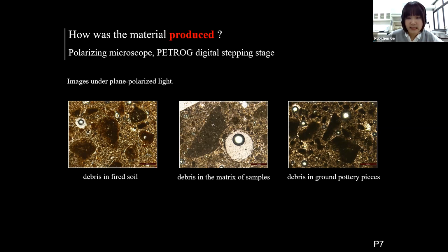To verify this possibility, we ground the pottery fragments for comparison. Numerous angular debris was observed with great similarity to the samples, the third picture. Based on all of the evidence above, this adhesive material was probably made of grains ground from potteries. The similar firing temperatures and compositions suggest the adhesive material is related to the statues.